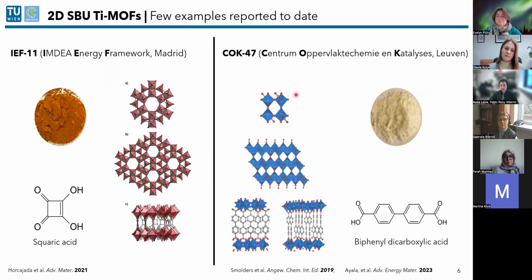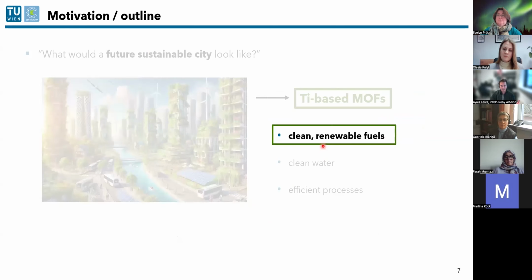The other structure that has been described is COK-47. This is the top view, and this is the side view. In this case, they used biphenyl dicarboxylic acid. It's a different coordination, so we have a carboxylate, and the color is also different. So both these materials have been used for water splitting applications, and we were very interested in COK-47 because there is the possibility to control particle size and defect content, and we wanted to investigate how that has an impact on the activity.